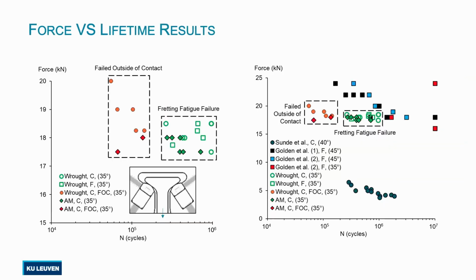Here are some results. So let's talk about the results. First, we tested and plotted the forces against the number of cycles. What you see here is grouped in two cases: we have wrought material and AM material, and we have some fretting fatigue failures, and some of them failed outside of the contact.